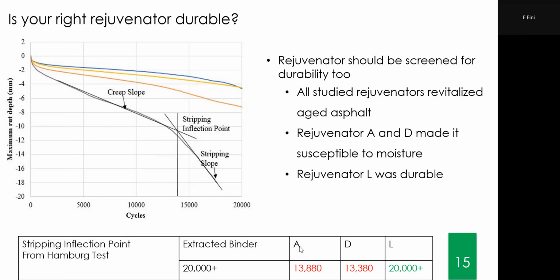When we rejuvenated it with A, now we get 13,000. That means it's more moisture susceptible than the aged asphalt was. When we added D, the same thing happened. Only L did not reduce the number of cycles at the inflection point. The inflection point here is used as a sign of stripping. You can see here with the schematic, when the inflection point happens, you get two slopes: a creep slope here, and then a stripping slope. The cut here will tell you how many cycles it takes to get to this inflection. In this case, aged asphalt had 20,000 cycles before it got to the inflection point.